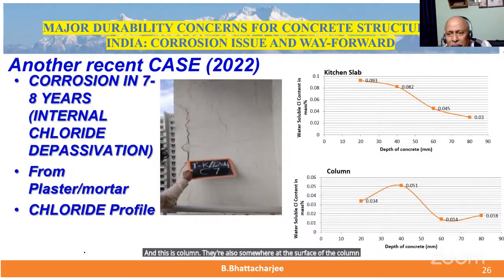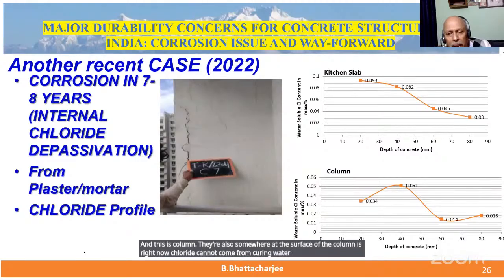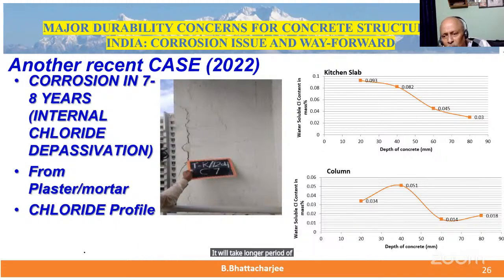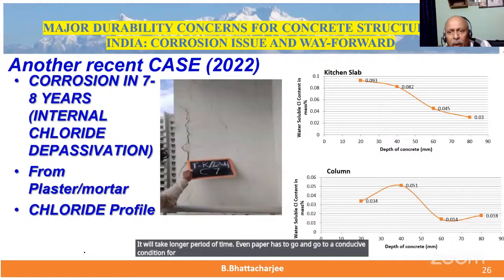Now, chloride cannot come from curing water, because diffusion of water takes very long time. Diffusion coefficient is 10 to the minus 12 multiplied by something. It will take longer period of time. Even vapor has to go to a conducive condition for chloride, take the chloride along with it, because that will take place by what is called advection process. Liquid in solution form it has to go. That will take very long time.